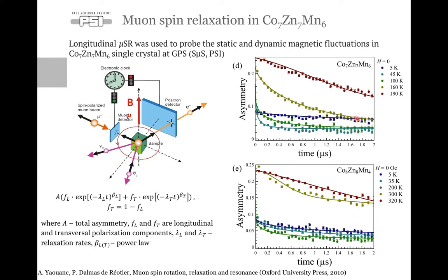But as we cool down and go close to the TC, we have larger asymmetry change. So paramagnetic fluctuations are slowing down and enter the muSR time window. And then once we reach the static magnetic ordering below 150K, we see very fast polarization decay that suggests some static helimagnetic ordering that immediately depolarizes the muon beam. But once we go below the spin glass ordering temperature, we see that the asymmetry function firstly decays very fast and then has this very flat tail that is due to the so-called slow magnetic fluctuations.